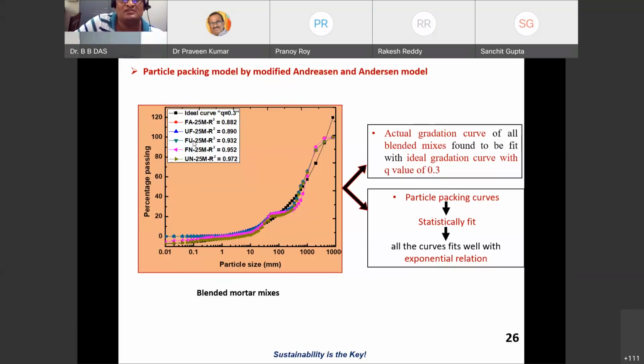So similarly, the ultrafine nanoparticles. Here it was 0.89, and you can see the ultrafine nanoparticles 0.972. That is the beauty. Here, cement is some micron size particles, ultrafine fly ash is some micron size particles, and nanoparticles are 10 to the minus 9, still smaller. So there are three varieties of particle size we are mixing, and that's why it is giving me the best of it for you. All right.